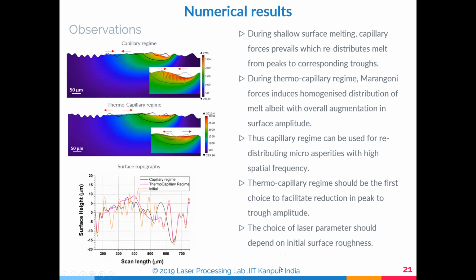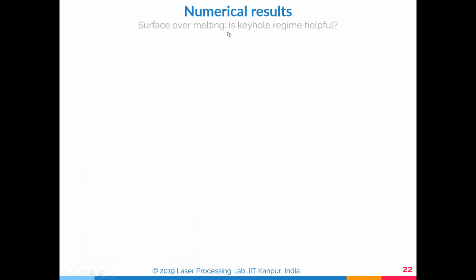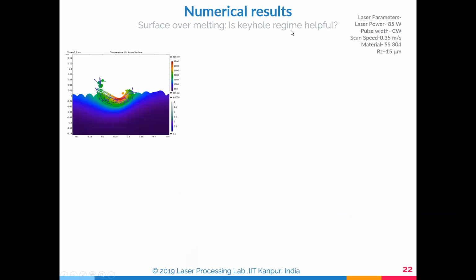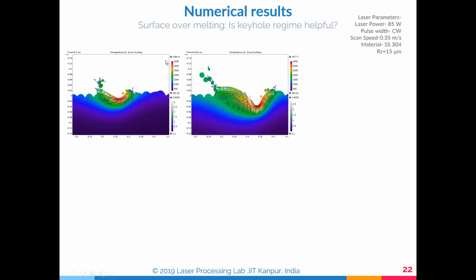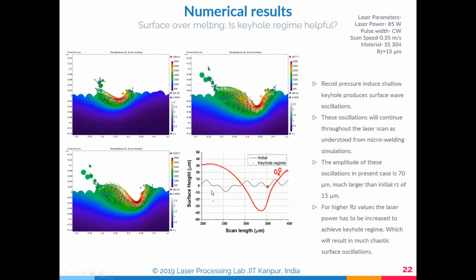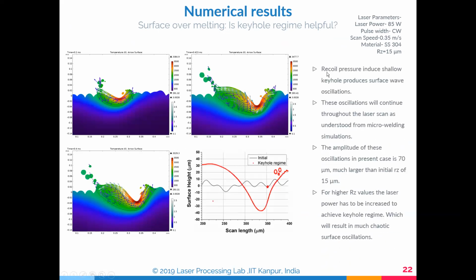Thermocapillary regimes should be chosen first to facilitate reduction in the peak, and the choice of the laser power depends on the initial roughness. Is surface overmelting in the keyhole regime helpful? This is the other thing which we try to see. And these are the keyhole effects we looked at. And then we figured out, yes, the recoil pressure induced shallow keyhole produces surface wave oscillations. These oscillations will continue throughout the laser scanning while it is used.